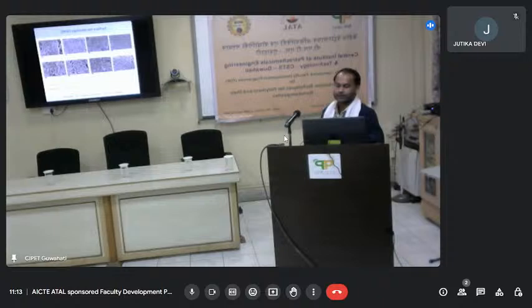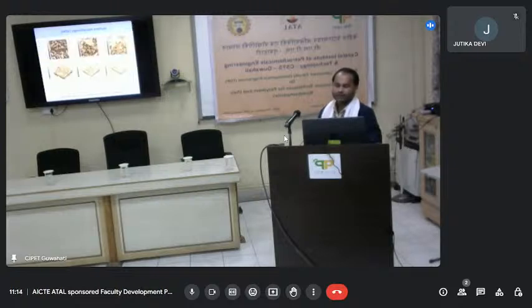We have seen that because of the plasma etching, there are many changes in surface morphology, mainly the surface roughness, which increased drastically. But when we went through FTIR as well as XPS studies, we saw that the bulk properties remain unchanged, instead of the surface properties. These are the top and bottom views of those experimental works. Then these are the AFM images, and the surface of the membranes can be visualized easily from this.